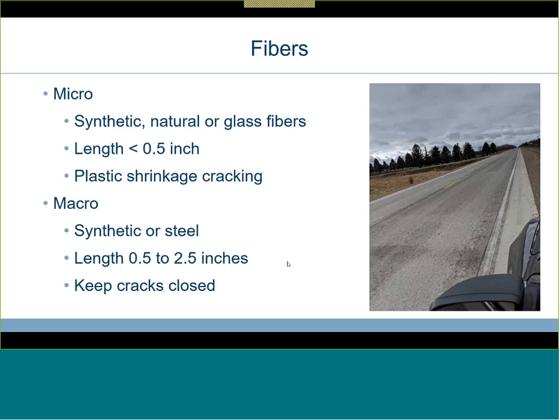To test this out, we've built a traffic circle in central Minnesota, and in northern Iowa, we put down a test section here with a fairly high dose of macro synthetic fibers, and we didn't saw it at all. It's cracked out at about 60 feet spacing. We're keeping a close eye on those cracks to see whether or not we're still getting load transfer between the panels. But so far, the county engineer who owns this is very pleased, because one thing he does not have to do is to maintain the joints. At the moment, the last time I rode this was in November, the ride was still really good.